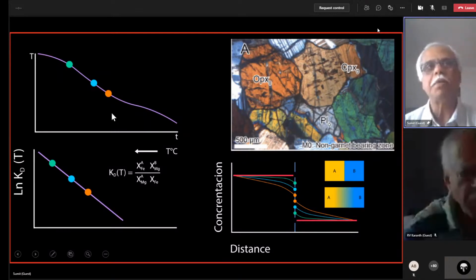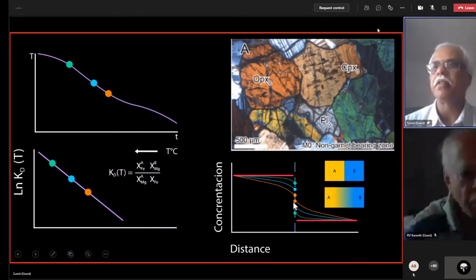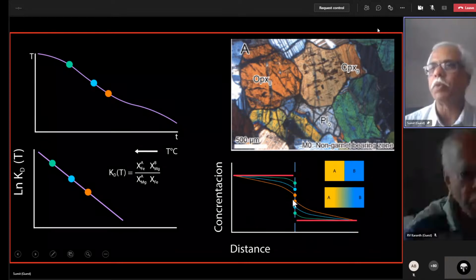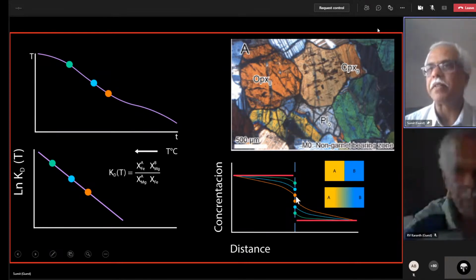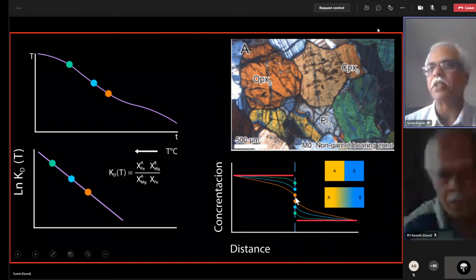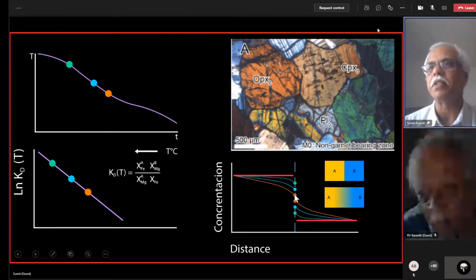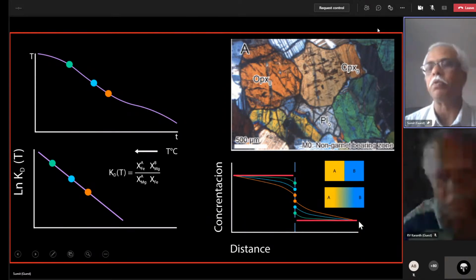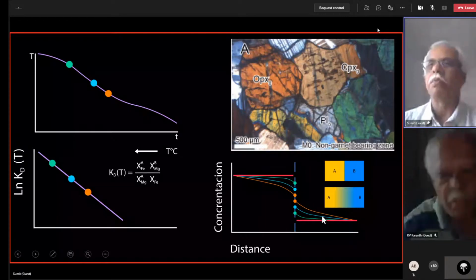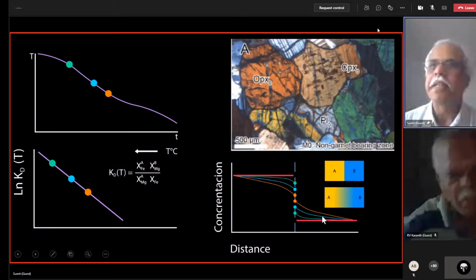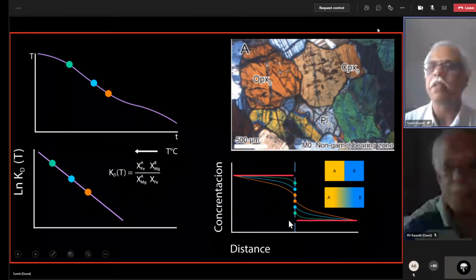And if you drop the temperature even more beyond that, then it turns out that the kinetics becomes so slow that even the interface cannot react. So it just freezes right at this point. And today, the crystal that you see would give you this orange measured zone profile. Now, from what I've been telling you, it should be clear that this actually is a continuous tape recorder of what is going on in the rock.